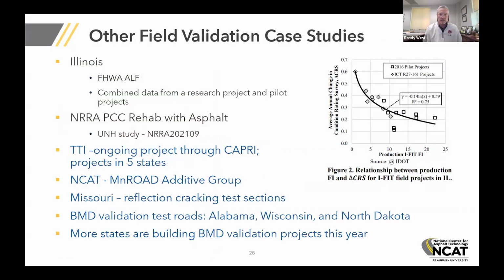There are other studies that are important to mention. I mentioned the Illinois Flexibility Index test. They had initially done some correlations with an experiment on the FHWA accelerated loading facility. And then they followed up with some other correlations, which I'm showing in a little chart off to the right, that's really combining data from a research project and their pilot projects in Illinois that shows a good relationship between flexibility index and the rate of cracking that they observe on projects in Illinois.